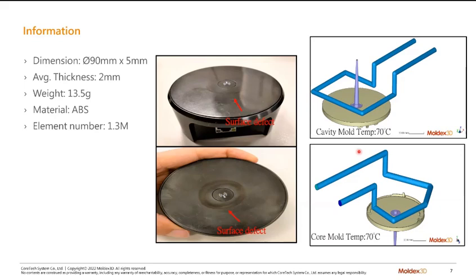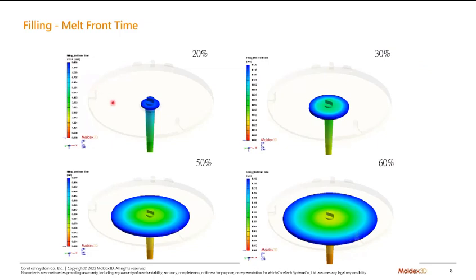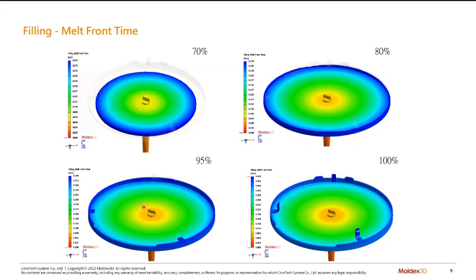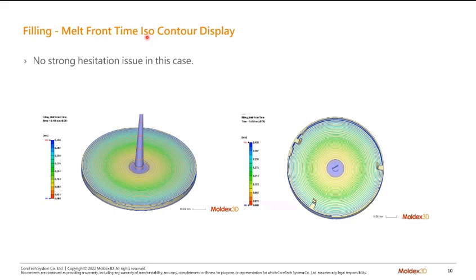So they think maybe this is caused by the flow. They check the melt front time, but as we can see here, it looks quite smooth, so it doesn't show any hesitation issues. Or we can just use this ISO contour display method. We can check the lines in between. The distance between each line means the same time increment. So if any lines get closer, it means there's a hesitation issue. But you can see the distance in between each line is quite equal, so it doesn't have a strong hesitation issue in this case. So it's not really a flow mark problem.